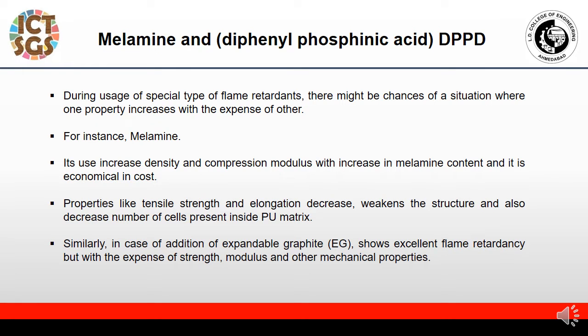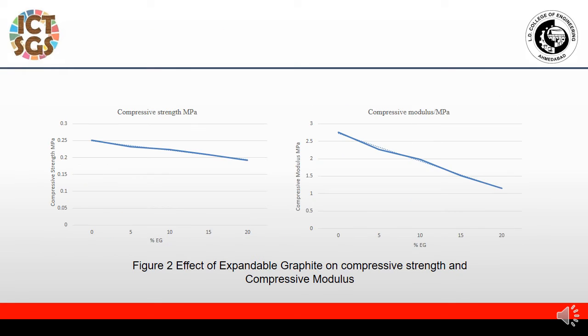polyurethane matrix. Similarly, the addition of expandable graphite into the polyurethane foam shows excellent flame retardancy, but at the expense of the strength, modulus and other mechanical properties. Here, both figures show the effect of the expandable graphite on compressive strength and compressive modulus of the polyurethane foam. It shows a decrease in the compressive strength as well as in compressive modulus with increase in the percentage content of the expandable graphite.